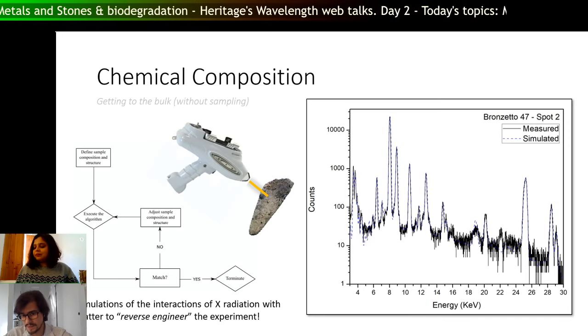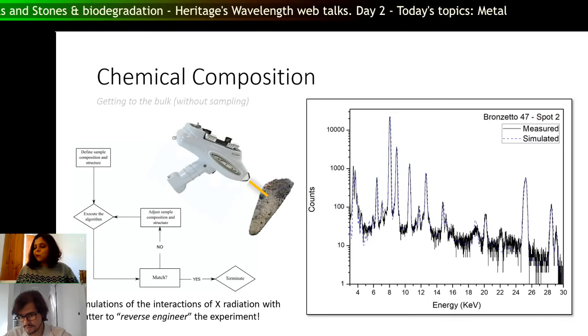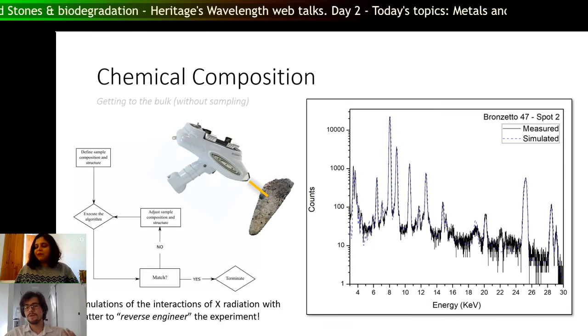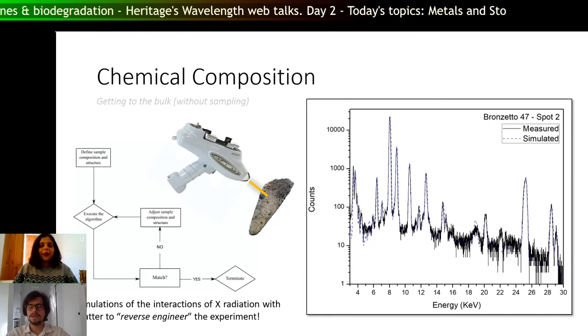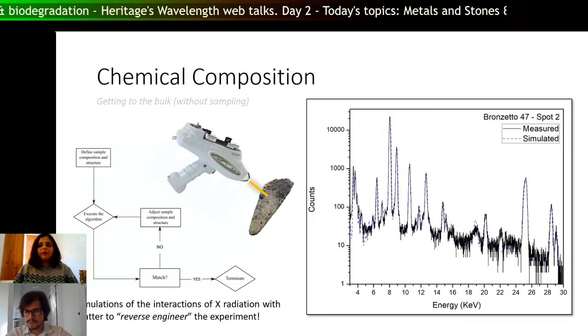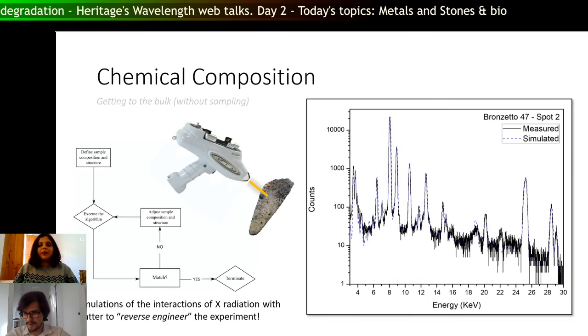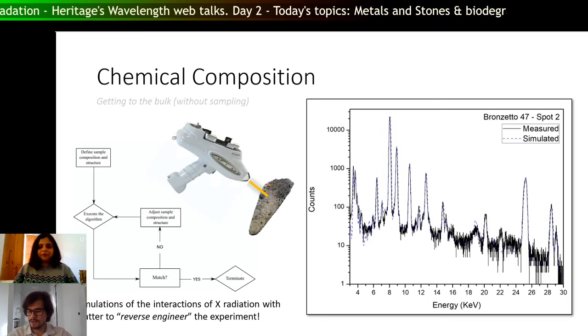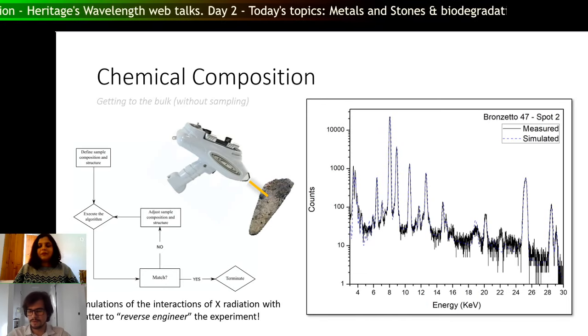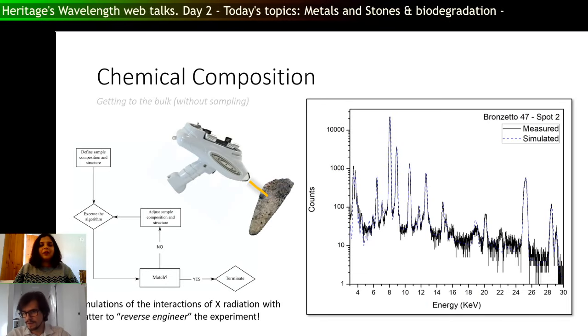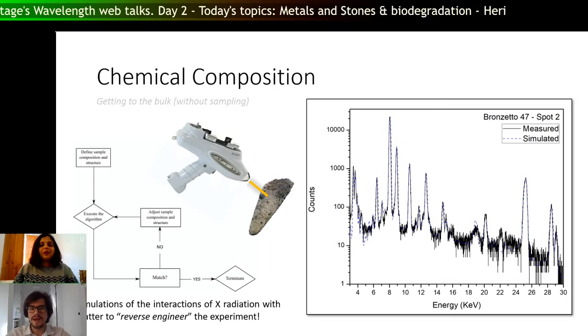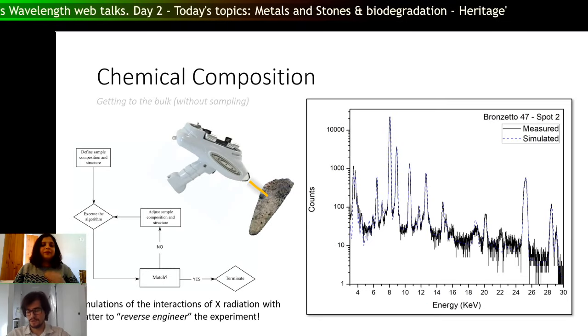So you also have peaks here that should be from iron at around 6.5 kilo electronvolts. So you know kind of an initial composition. And by looking at the sample surface and the colors of the patina, you can guess, oh, there should be a lot of cuprite, maybe some tenorite or posnjakite, I don't know. By the colors, you have an idea of what should be your corrosion layer.